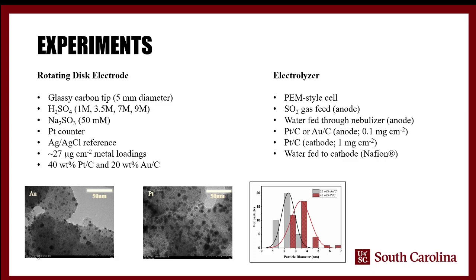And that could be a couple of different ways. First of all, it could be that the sulfuric acid just acts because its viscosity is higher. Sulfuric acid could just slow down diffusion of the ions to the electrode, which would in turn lower the apparent activity of the catalyst. On the other hand, sulfuric acid could actually cause a reduction in activity of the catalyst via damaging the catalyst itself, or by attaching to the catalyst surface and occupying catalytic sites on a longer scale basis, whether it's permanent or a time scale that's much longer than the typical reaction time scale. And so we need to understand how sulfuric acid concentration affects that, because that's going to affect the actual operation